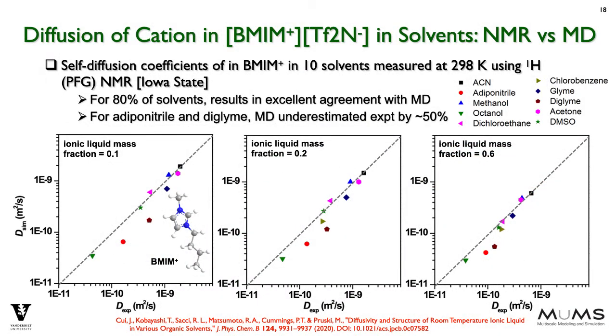Inspired by our calculations, a set of collaborators from Ames National Lab used pulsed field gradient NMR to measure the diffusivity of the BMIM cation in 10 of the solvents we studied computationally. In these figures, the diffusivity from simulation is plotted as a function of the experimentally measured diffusivity for 10 solvents, shown as colored symbols, and at ionic liquid mass fractions of 0.1 at the left, 0.2 in the middle, and 0.6 at right. Points lying on the y equals x line indicate excellent agreement between simulation and experiment. Quite remarkably, for 8 out of the 10 solvents, the MD simulations were spot on. Only for adiponitrile and diglyme were the simulations off, and this is probably due to inadequacies in the force field in the simulations.